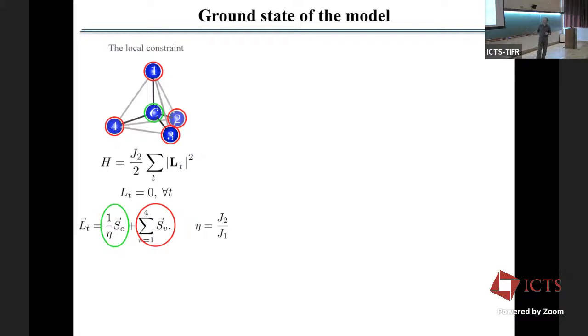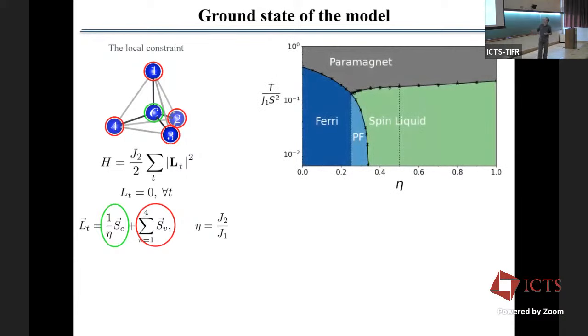Because what happens is that for small value of eta, this central spin will dominate. For example, imagine that eta equals 0.1. So 0.1 means that J2 is very small over J1. Then you have this central spin times 10 plus all of this. And you see that since all of these spins are normalized, if you have 10 here, the sum of 4 unit spins cannot cancel out this one. So this term here will necessarily be finite. And so what will happen is that this central spin will point in a given direction, and all of the corner spins will point in the opposite direction. And you will get ferrimagnetism.